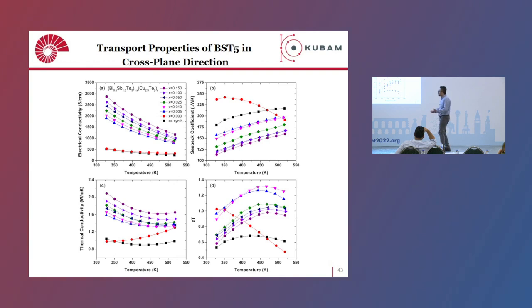Okay? Let's see the overall effect. This is our typical BST, with no heat treatment. The red one is what we made with 10 minutes of ball milling, and the others are 10-minute ball milling plus the copper telluride addition. At low temperature, it is comparable to our best material, the 10-minute ball milled material, but at slightly higher temperature, like 450 K, it outperforms. We reach a ZT around 1.3. It is quite an important improvement for this material.